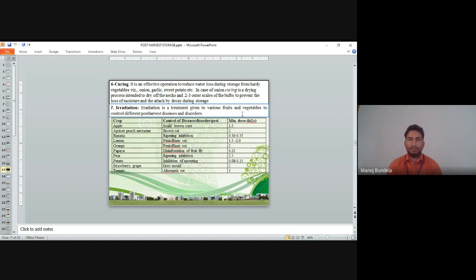Irradiation. Irradiation is a treatment given to various fruits and vegetables to control different post-harvest diseases and disorders. So you can see, like in apple, some examples like scald and brown rot, that we can control by giving irradiation of 1.5 kilogray for a kg. The apricot, peach and nectarines we can use for the brown rot disease. We can give 2 kilogray irradiation. Banana ripening inhibition 0.3 to 0.35. Lemon penicillium rot we can use 1.5 to 2 kilogray dose of irradiation. Like this, for different fruits we can use different irradiation doses.